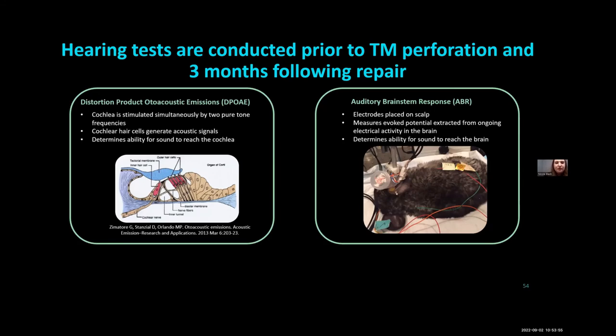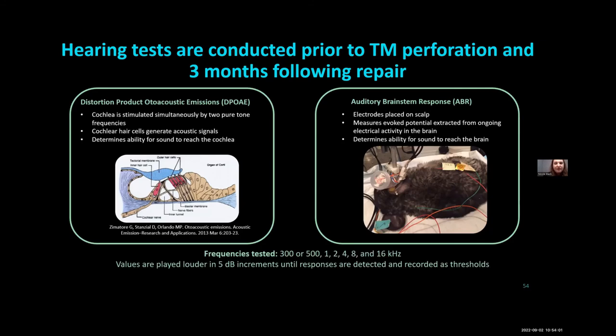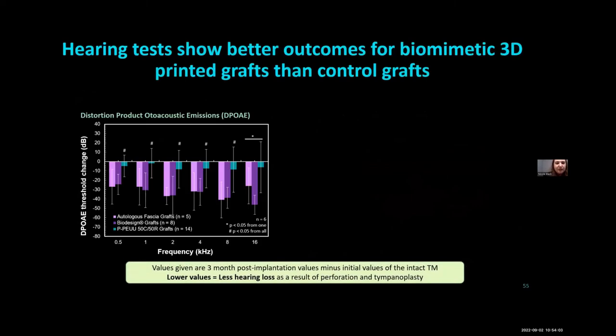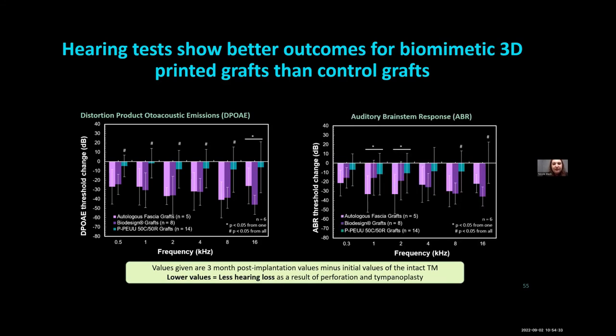And so you can monitor these thresholds both initially and then 3 months following repair and compare how the hearing has improved over time. In all of these plots, essentially values closer to zero are better, because this means that the hearing has been restored closer to baseline levels. In the case of DPOAE, you can see for fascia grafts and the biodesign, there's still a substantial hearing loss of about 30 to sometimes 50 decibels at most frequencies following tympanoplasty, whereas with the 3D printed devices, it's closer to about 10 decibels. So substantially better hearing after this procedure, closer to their normal levels.